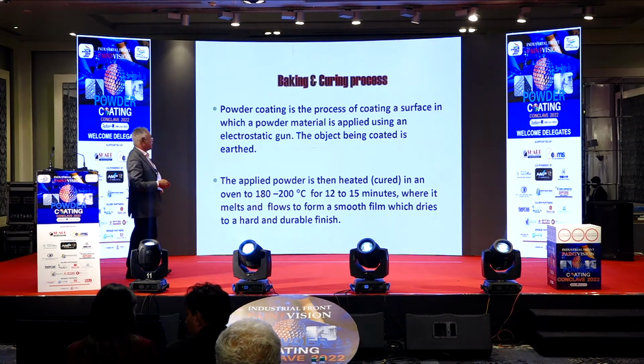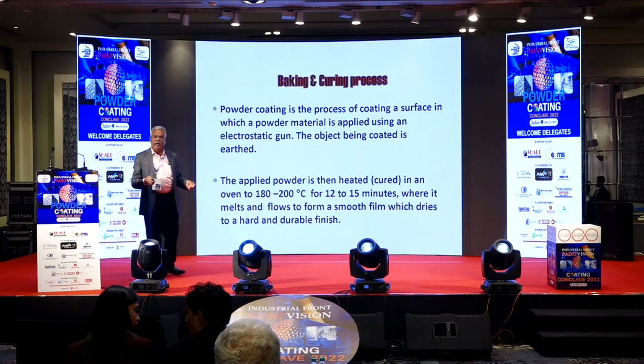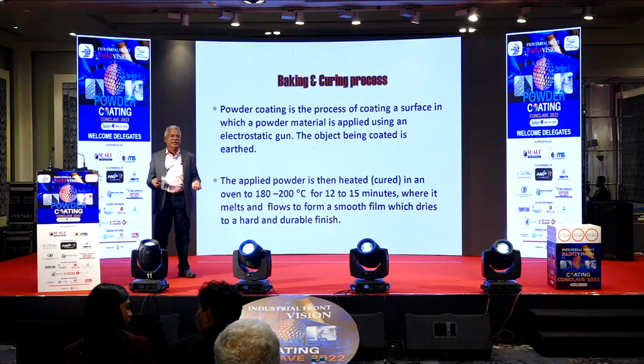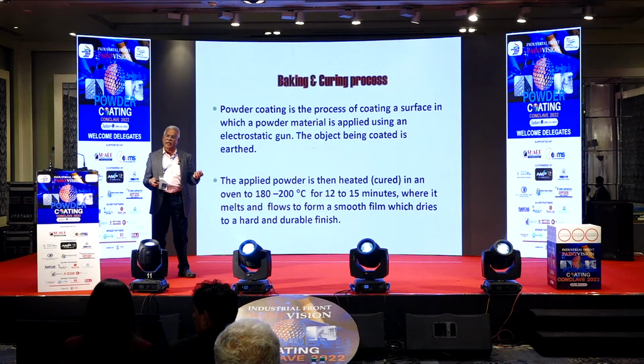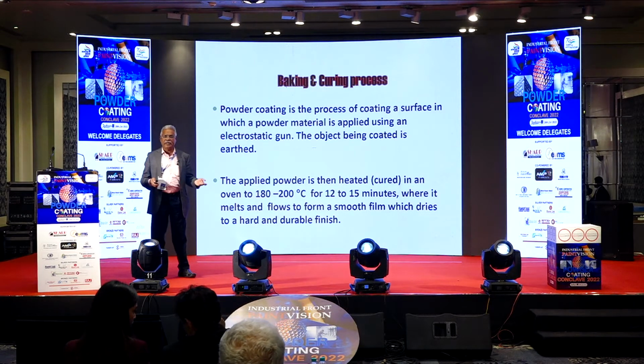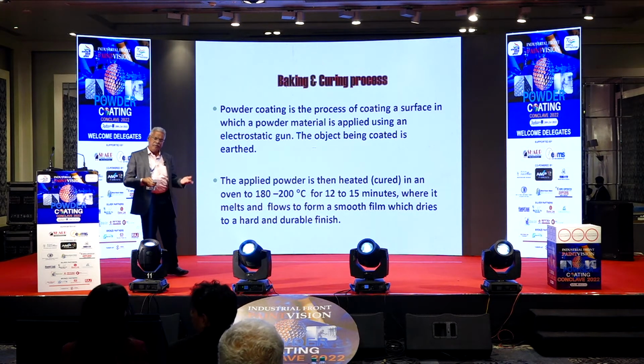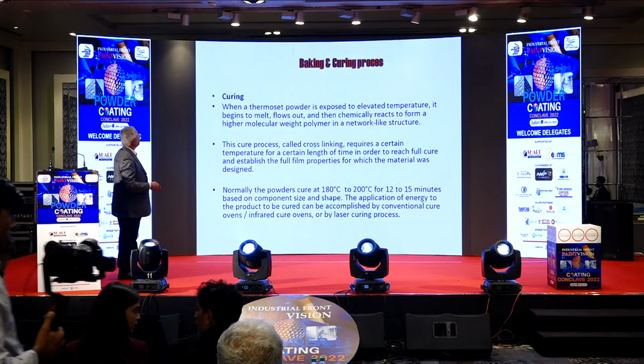Generally, baking and curing: a hybrid system will be baked at 180 degrees for 12 minutes, and pure polyester will bake around 200 degrees for 12 or 13 minutes. Even in polyurethane, it will be the same, baking and curing.